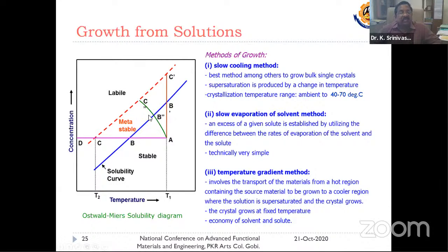Whereas in this region, you won't get any nucleation, but you can grow bulk single crystals by placing a proper seed within this one. Seed means a portion of the crystal cut from the already grown single crystal. When you place a seed here, the surface of the seed will grow using the excessive concentration available in this region. It is known as the metastable region.